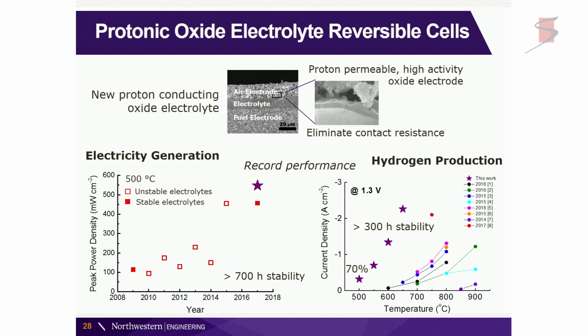In this case, electronic leakage is not a problem because you're operating in forward. I can have a conversation with you in the coffee break to explain why electronic leakage does not impact the fuel cell results, but it can be problematic for the hydrogen production. We're at 70% Faradaic efficiency at these lower temperatures. And again, if we compare the current densities to prior work that's all been done with oxygen ion conductors, you can see that our current densities are substantially higher. And in these cases, again, no real measurements of Faradaic efficiency. So we can see that this is really moving this forward.